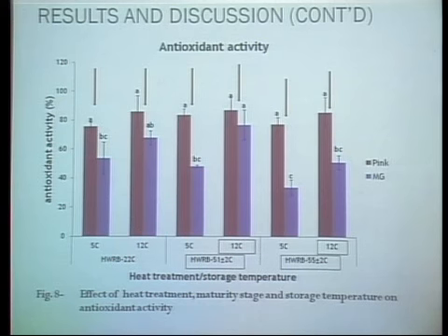But in the decay, we noticed that there was decay in the control at 12, and there was some decay also at 5. So if we are considering which treatment is better, then we will consider these two heat treatments, since here there wasn't any form of decay or any chilling injury. So in the antioxidant activity, this heat treatment was able to maintain or improve the antioxidant activity.